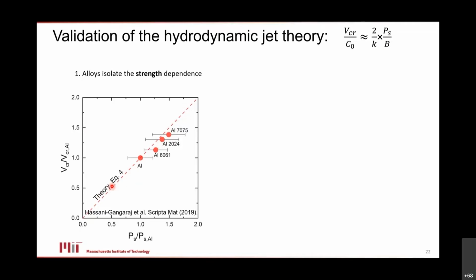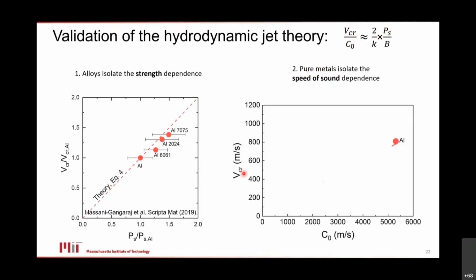The second thing you might do to validate this theory is try to get rid of the strength and focus on the elastic properties. And it turns out you can do that reasonably well if you're willing to work on high purity metals. If you work on high purity metals, then the strength is proportional to the bulk modulus. And so this entire term here on the right turns into a constant. And the only dependence you have left then is the speed of sound. So you expect that the critical velocity becomes a function of the speed of sound. And indeed, when we do a bunch of tests on high purity metals, that's exactly what we find. These guys line up, they follow the scaling law, it goes through the origin as expected.